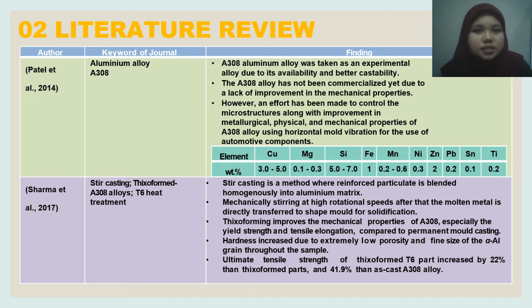2014. Next, stir casting is a method where reinforced particulate is blended homogeneously into the aluminium matrix by mechanically stirring at high rotational speeds. After that, the molten metal is directly transferred to a shaped mold for solidification. Thixoforming improves the mechanical properties of A308 material, especially the yield strength and the tensile elongation, compared to permanent mold casting. Hardness also increased due to extremely low porosity and fine size of the alpha aluminium grain throughout the sample. The ultimate tensile strength of the thixoformed T6 part increased by 22% over thixoformed parts and 41.9% over as-cast A308 alloy. This was extracted by Sharma et al. 2017.